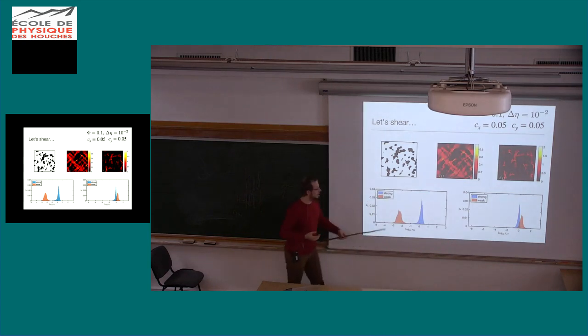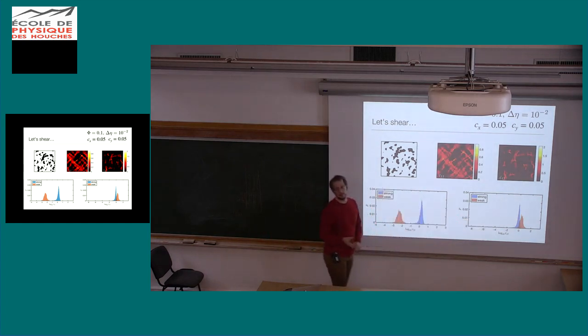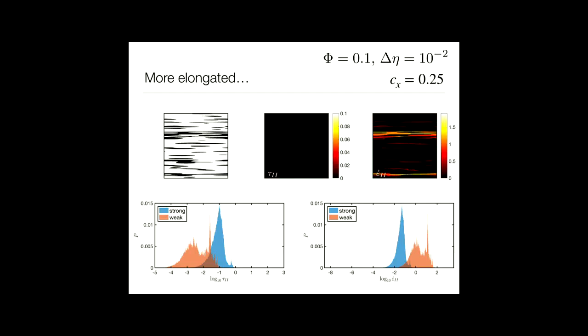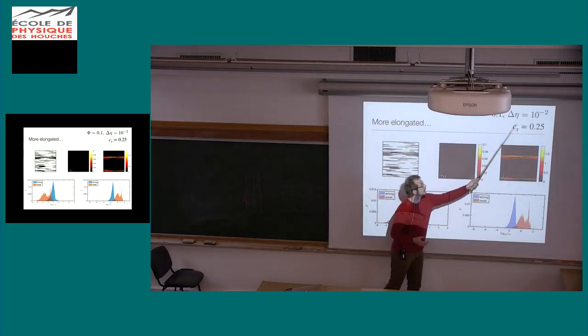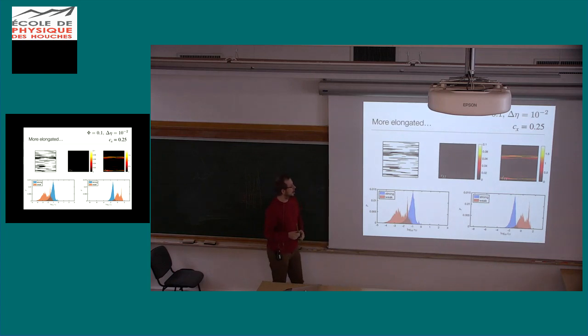And what you see is already: in the weak phase you have less stress because it's weaker, but it is also being more deformed, which is quite intuitive in the end. Okay, and then I can basically elongate the whole thing. So what I say is, now set my correlation length in the x direction to a larger value, and what you then get are those elongated inclusions.